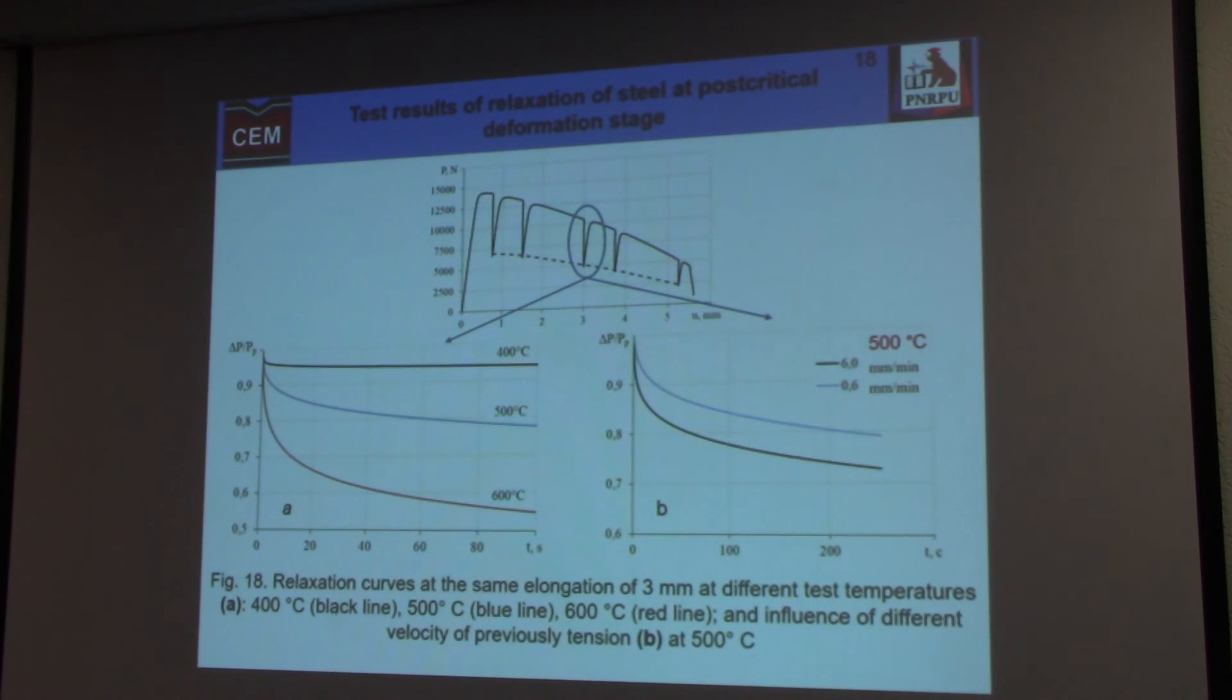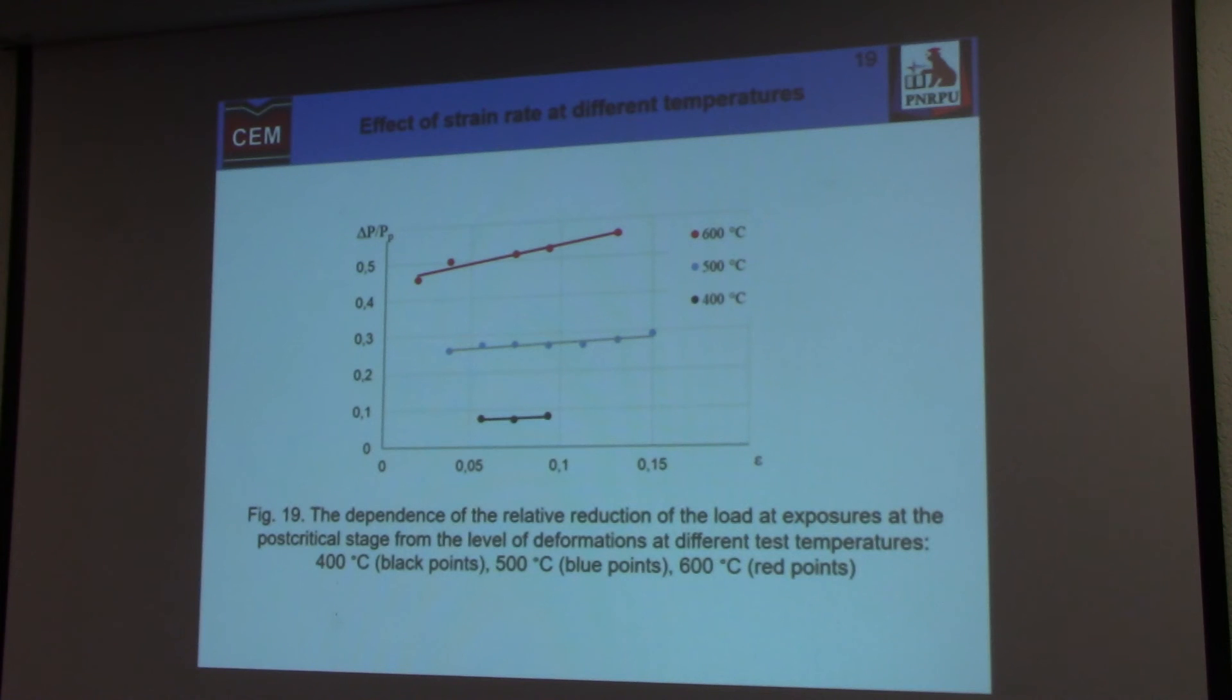Here you can see the same results for same elongation of 3 mm for different temperatures. And you can see that intensity of relaxation depends on temperature and depends on velocity of previously active deformation at the same temperature.